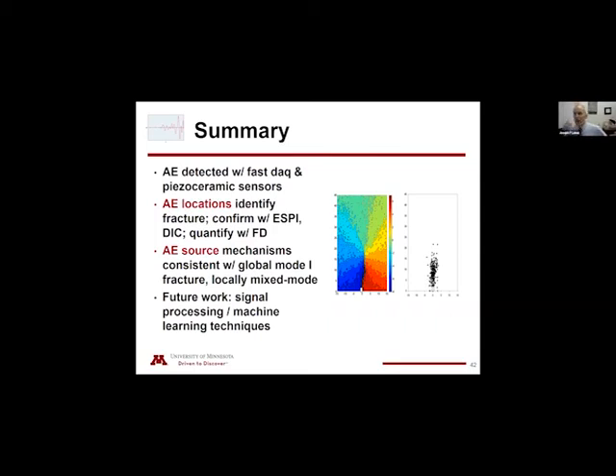Okay, I should have mentioned that. Your first question, John: why we're seeing this mixed mode, well, there is some tortuosity certainly within the rock specimens. These experiments were just conducted this summer, and we're still analyzing the results, at least for the glass. I was surprised to see that behavior for the glass, but there could be, because the crack, strictly speaking, is not simply vertical. So there is some tortuosity. If you get a little crack that is not vertical, because of the opening in the X direction, there has to be a tangential component. So that's how I would explain why we see that.